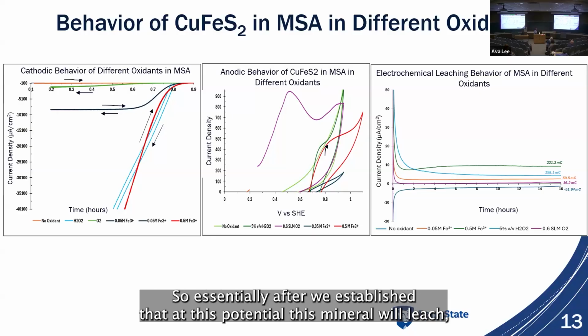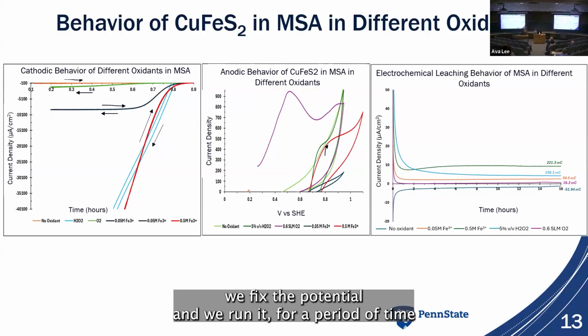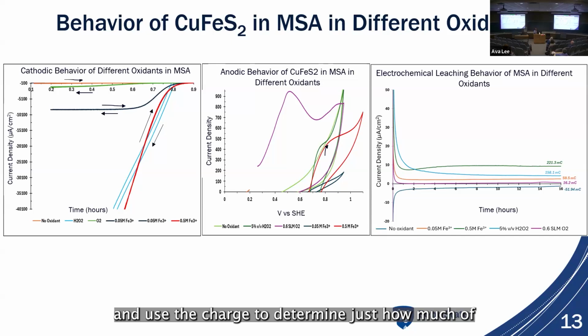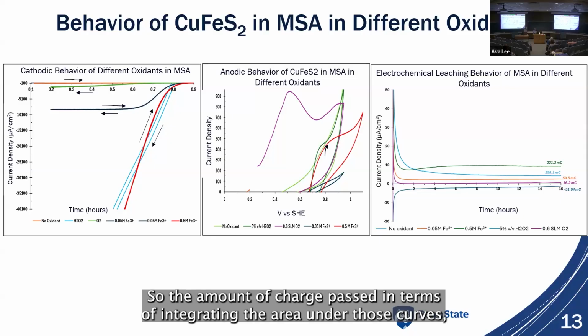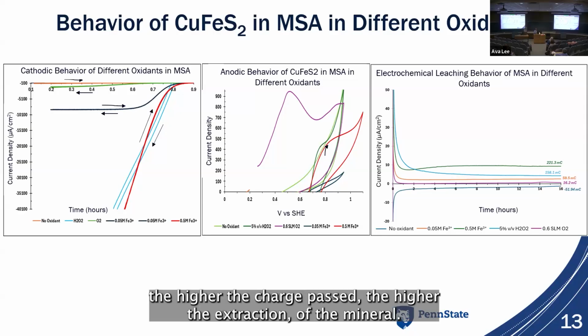So essentially, after we establish that at this potential this mineral will leach, we fix the potential, run it for a period of time, and use the charge to determine just how much we track the charge. So the amount of charge passed, in terms of integrating the area under those curves: the higher the charge passed, the higher the extraction of the mineral.